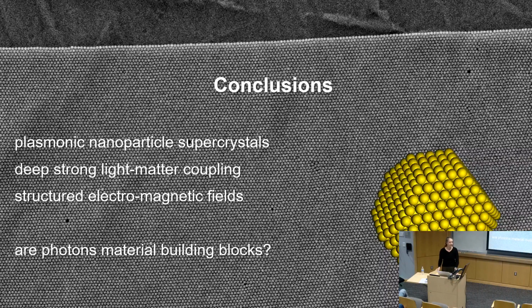So I wonder why you use the polystyrene polymer as a coating. Usually with polymer, we try to get a superlattice. We don't use polymer because it's really hard to control the polymerization degree, so that you don't have a uniform coating. It's not polymerized. These polystyrene brushes are put on and they're just pushed into each other. But you still have a longer brush, and if it's a shorter brush, it can be really hard to form a superlattice. So this chemical process, I just wonder why they choose polymer.